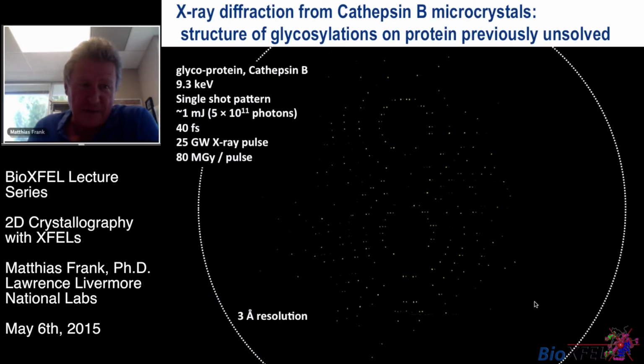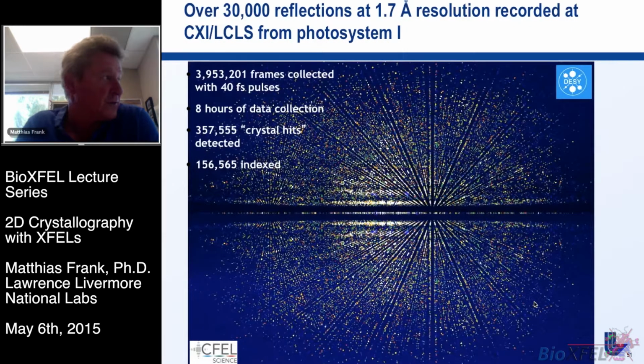Here's a diffraction pattern. Again, about the same parameters, 9 keV, 40 femtosecond pulse. Now, one thing I would like to stress is that in order to get really enough data to reconstruct the structures, you have to hit a lot of these microcrystals, because each crystal is in a random orientation and only gives you Bragg reflections that correspond to this random orientation. So you need to have a lot of hits of crystals that are all in different orientations to probe the whole Fourier space and all the reflections that are possible.